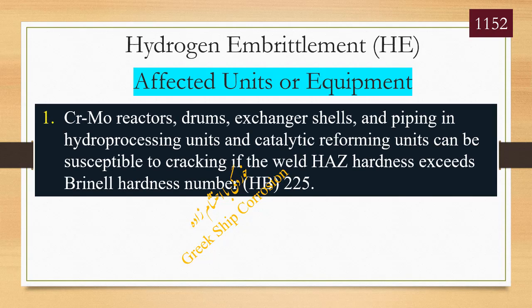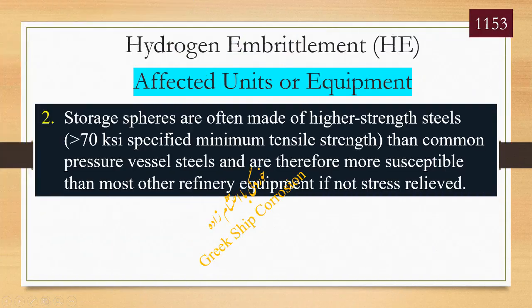Affected units or equipment. 1. Chromium-molybdenum reactors, drums, exchanger shells, and piping in hydroprocessing units and catalytic reforming units can be susceptible to cracking if the weld heat affected zone hardness exceeds Brinell hardness number 225. 2. Storage spheres are often made of higher strength steels, more than 70 KSI specified minimum tensile strength, than common pressure vessel steels, and are therefore more susceptible than most other refinery equipment if not stress relieved.